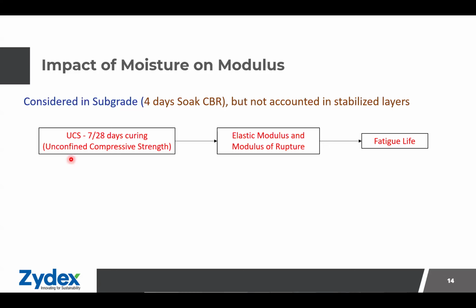What the current framework is that we are measuring the UCS in 7 or 28 days, depending upon the hardening agent that we are using, and then using empirical equations or the 4-point bending test, we are finding out its elastic modulus and then putting it into fatigue models and getting the life of a pavement. But in this, we are not actually capturing the effect of wet condition in the analysis. There's a 20% correction factor that is considered, but does it really account for moisture or does it account for other variabilities? That is questionable.